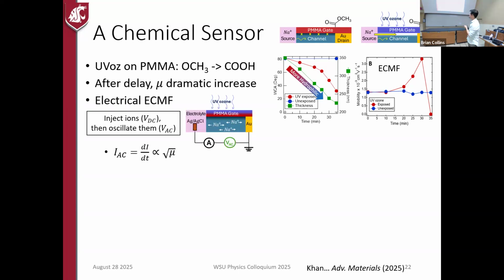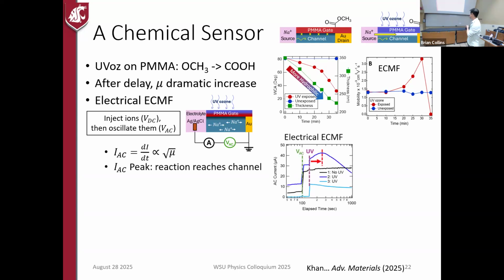So we developed this electrical version of the ECMF experiment where we're applying an AC voltage, where we have these ions and we're just sloshing them back and forth in the channel. And if they're higher mobility, we should get higher currents. And if you do the calculations, it's about proportional to the square root of the mobility. So we should get maybe not as big of a peak, but we should get a peak in AC current when we do this experiment. So here's the AC current versus time.